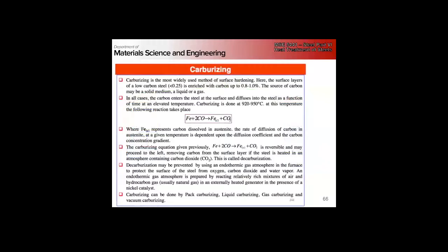And so this is very easy to do, again, with an oxyacetylene torch, right? If you just make it a rich flame, so you have extra acetylene going in, the incomplete combustion gives you plenty of carbon monoxide. And by heating your steel in that way, you can torch carburize and harden the surface of your steel, right? If we heat this in a carbon dioxide rich environment, this reaction goes backwards, and we can decarburize the steel and remove carbon from solution to soften it.